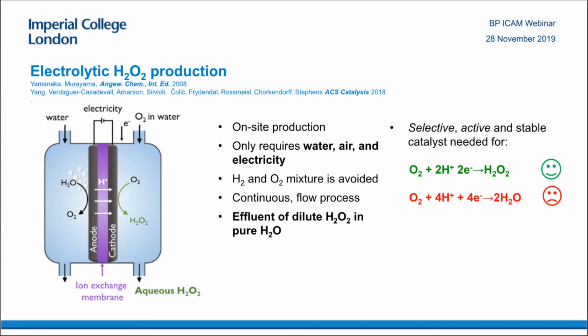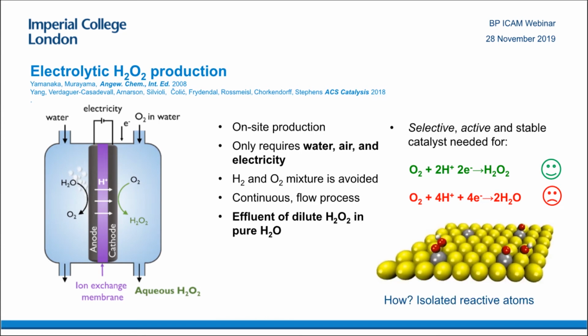However, what you need is a catalyst that's able to steer the reaction towards hydrogen peroxide, not the more thermodynamically stable product, which is water. So we looked at the literature. What we found is that people are making things like palladium gold catalysts, or even using cobalt porphyrins. The problem is that cobalt porphyrins are not stable and palladium gold is not particularly active.